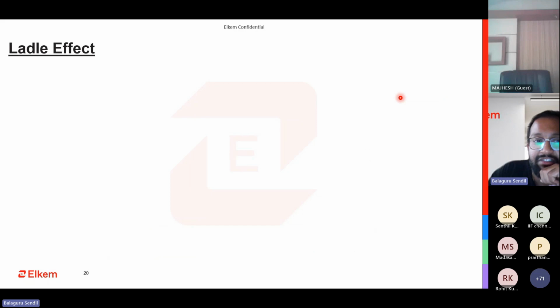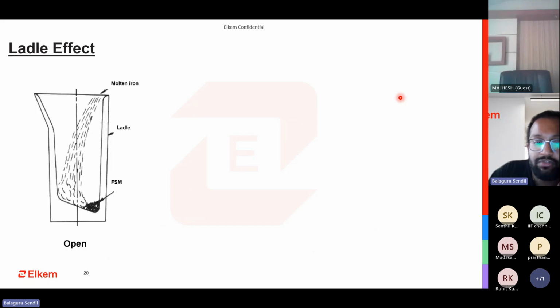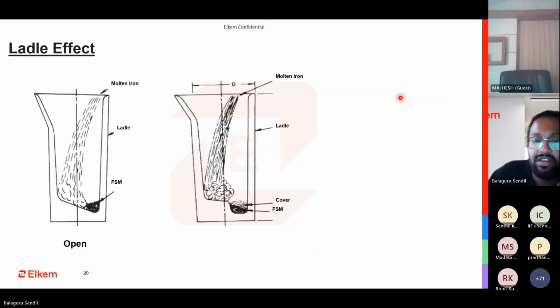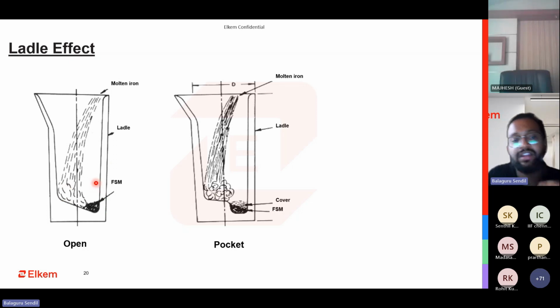The next is the ladle effect. So you are having different types of ladle. This is an open ladle. I've shown you this earlier. This is the pocket one you have. This is a very basic one. The metal stream is hitting here and it is going here. Open, sometimes you don't even have this curvature in your lining. We just have a flat ladle, and all these ladles have a nice L/D ratio. This is the length of the ladle and this is the diameter of the ladle. So it always should be in the ratio of more than 2. The length should be twice that of your diameter. That is the basics of it.